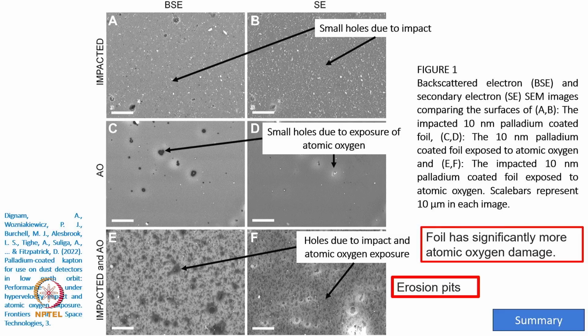In this case, what they have shown in A, and of course not only SEM, they have also shown the backscattered electron image, and they are comparing this surface. They see the impacted foil with a 10 nanometer palladium coating, and they found that whenever there is exposure of oxygen on this, it will increase the size as such.